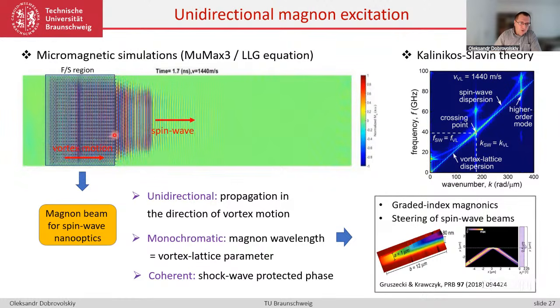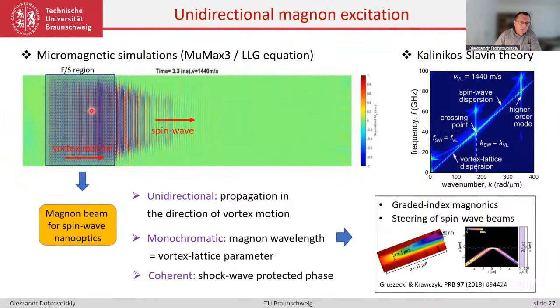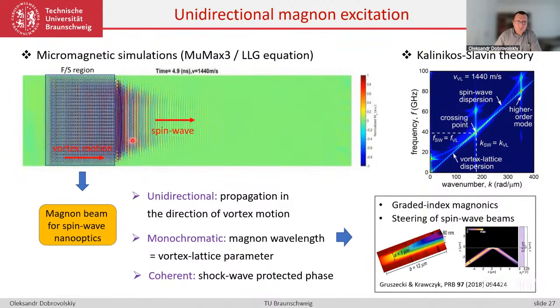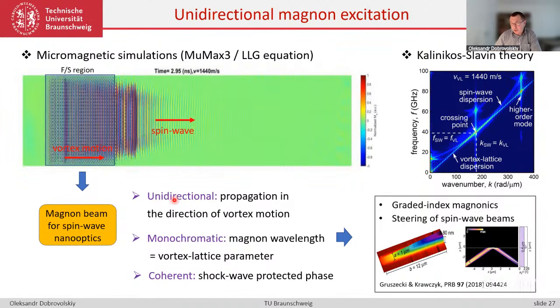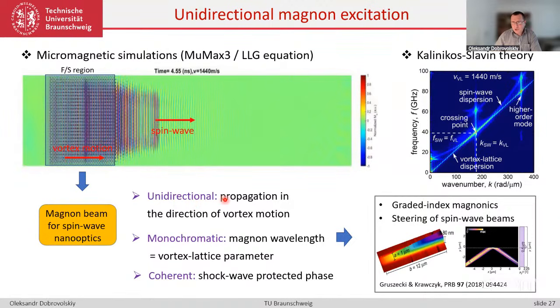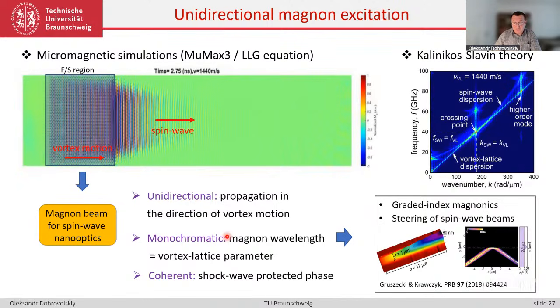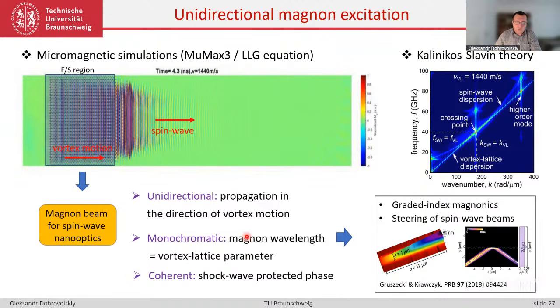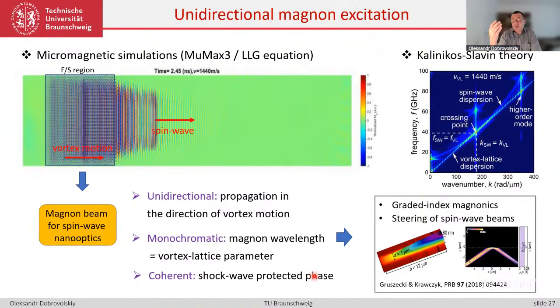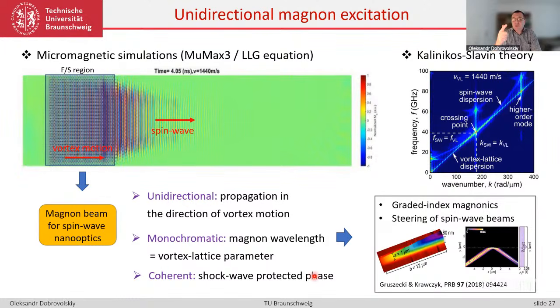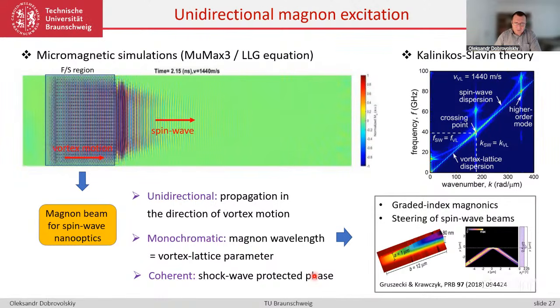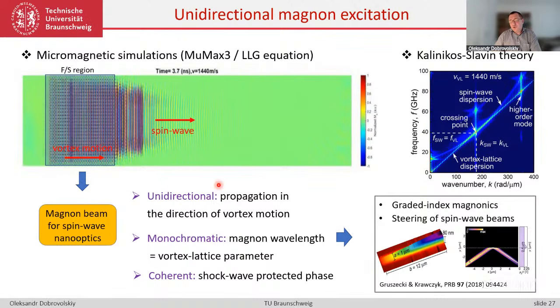So additionally and visually, we have here the propagation of spin waves from left to right. It's kind of a Magnon beam or Magnon torch, if you like, with very interesting properties of this Magnon generation. It is unidirectional, so the spin wave propagates in the same direction as the moving vortex lattice. The generated spin wave has a wavelength which is determined by the periodicity of the vortex lattice, and this interaction is coherent. It is shock wave protected phase because there is a back action of the spin wave which induces eddy currents, and these eddy currents couple to the vortex lattice which moves via the superconductor.